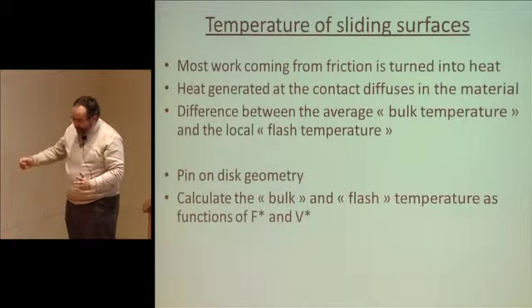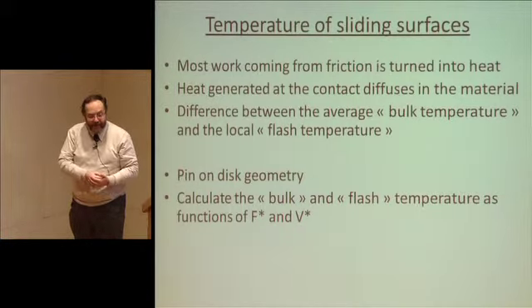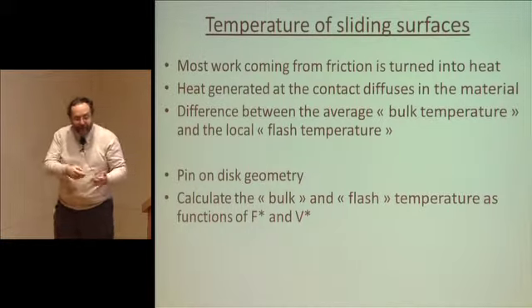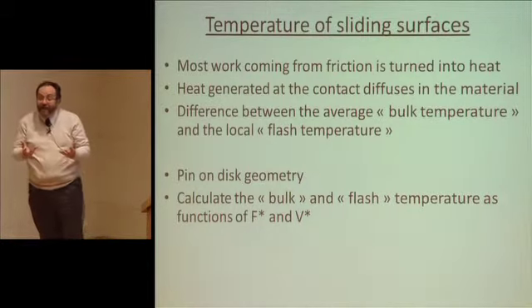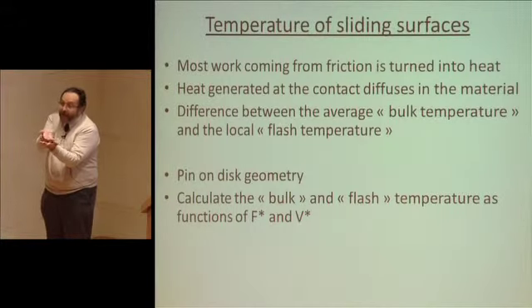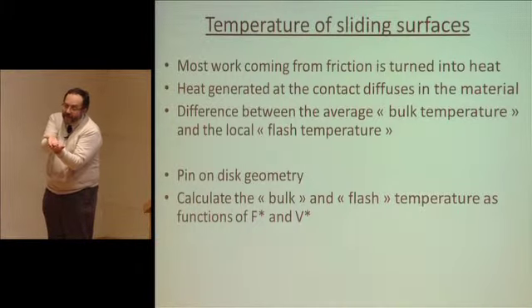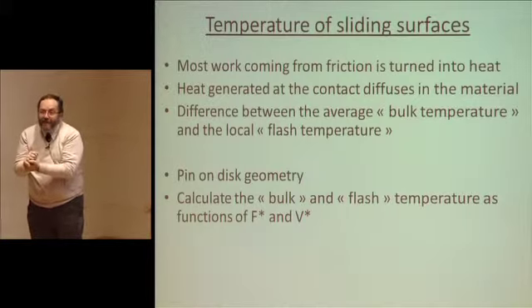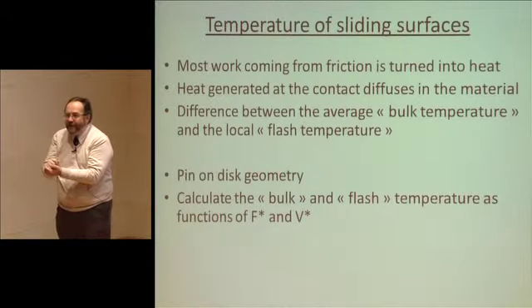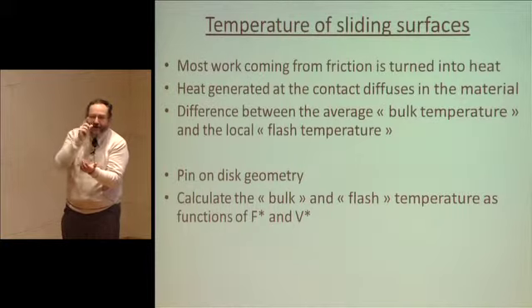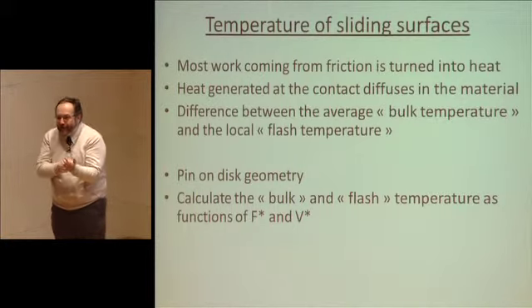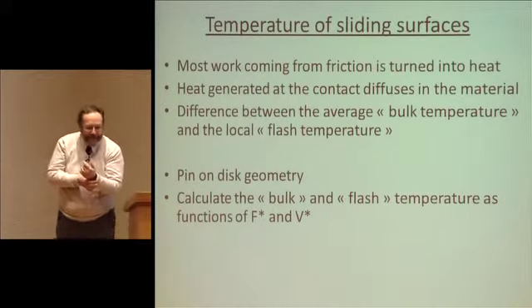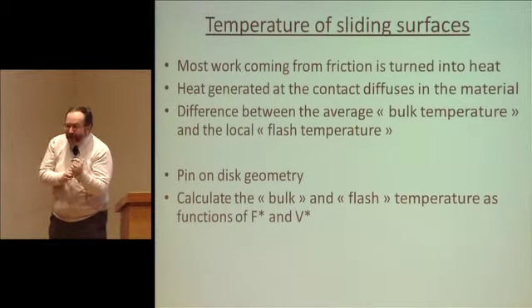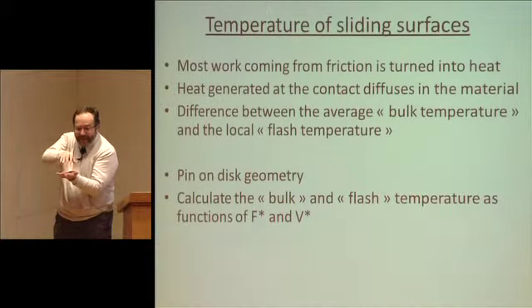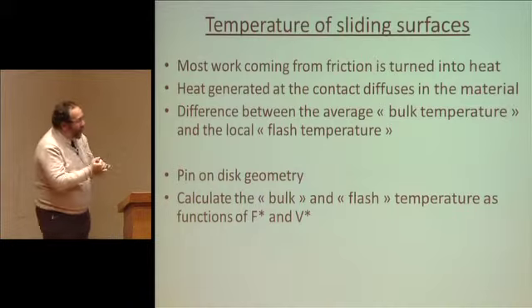which is that when you put a metal on top of a metal, the force required to move it does not depend on the surface in contact. So it's counterintuitive. And that's essentially due to the fact that the contact surfaces are the same surfaces that you're going to need to shear. So this was evidenced by Bowden and Tabor in the 50s and had actually already been tested by Maxwell. He wrote Maxwell's equations, and he thought it was okay to look at these friction forces, and he'd merely measured the electrical conductivity of two metal solids in contact.